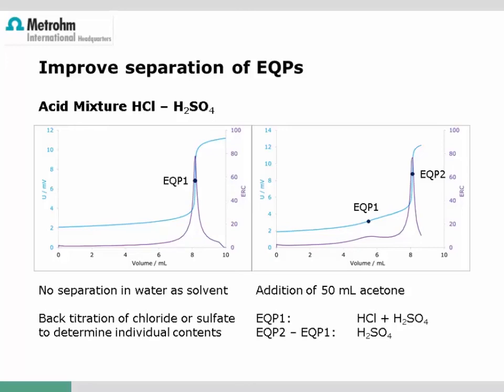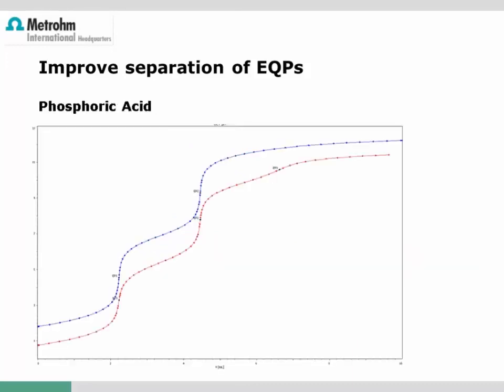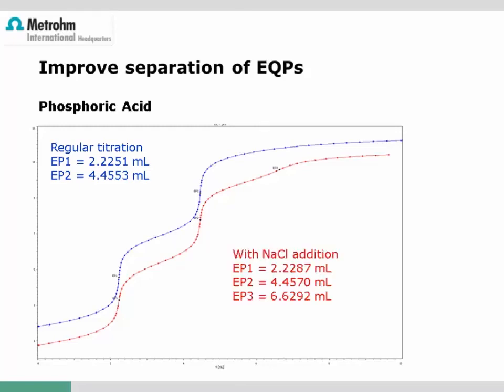But sometimes not even the use of organic solvents is necessary. For example, the addition of a salt like sodium chloride will also improve performance. This can be shown by this example, titration of phosphoric acid. The blue titration curve is a regular titration with water as solvent and no addition of sodium chloride. As expected, you can identify the equivalence points for the first and second proton. By adding sodium chloride, the pK value of the third proton is shifted and can then be detected. As you can see from the volumes of the equivalence points, the addition of the sodium chloride has no influence on the accuracy of the titration. The values are really identical.